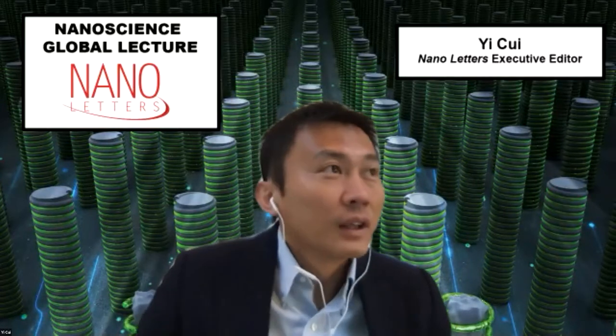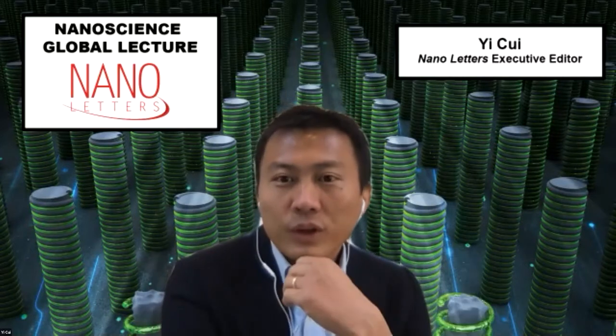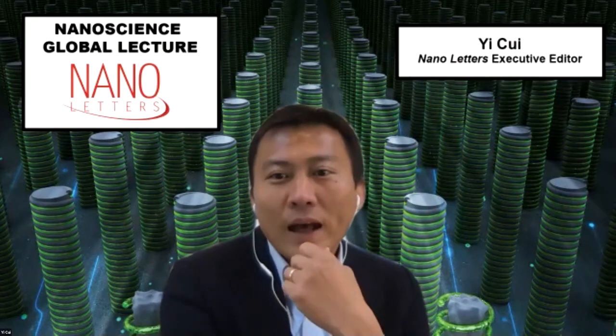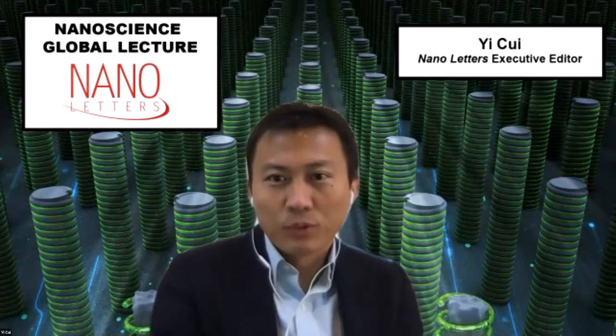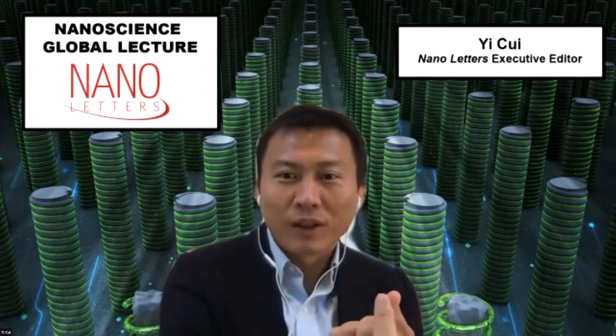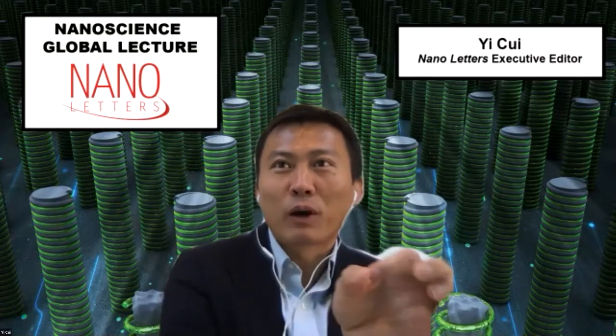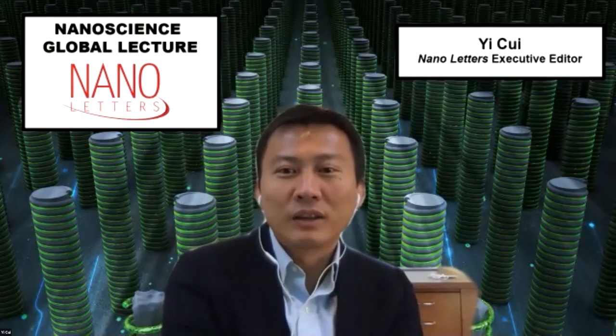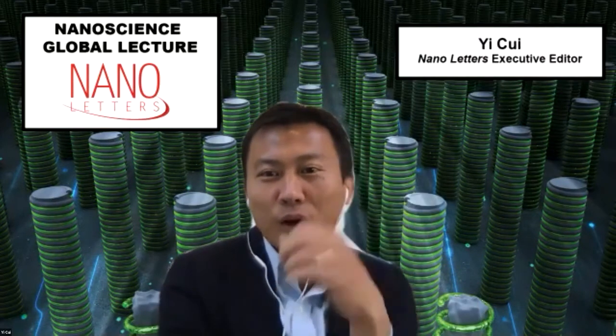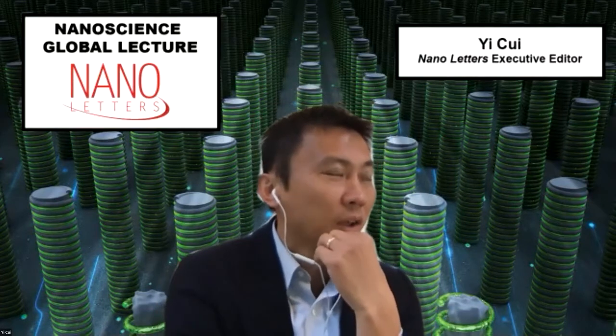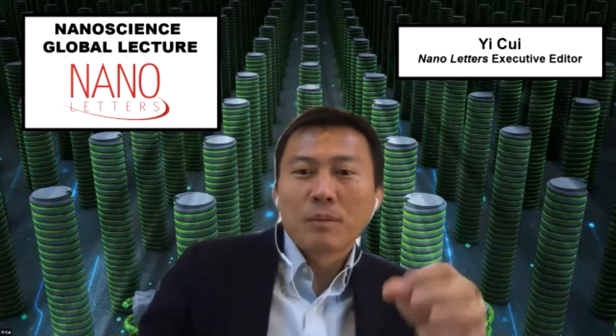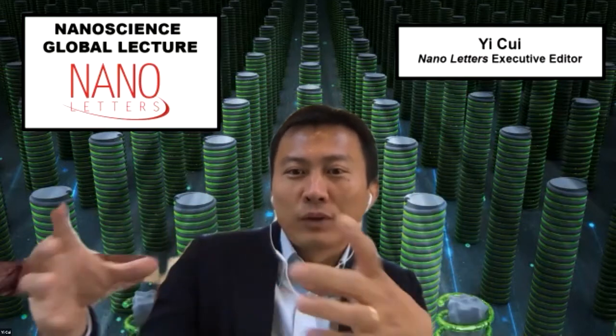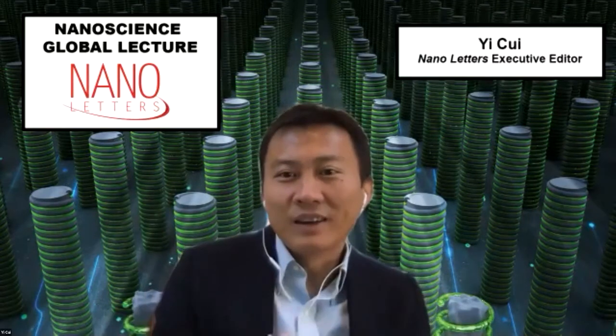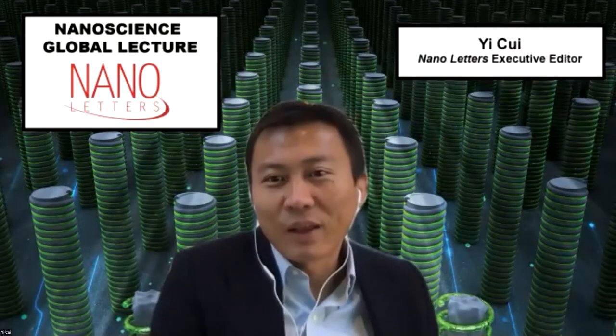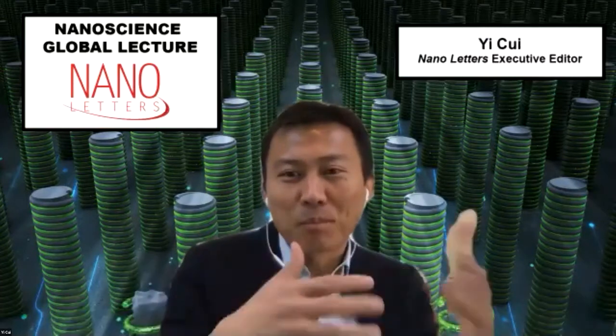My first question, Lars, related to the LED: I really like the argument from the early days of why you do nanowire LED. You grow these lattice mismatched materials, the nanowire cross-section is small, and that can anneal out a defect so it does not propagate into the whole wire. I remember that was the early thinking. So now compare wires with this micro disc or pyramid, and also compare to the bulk LED.